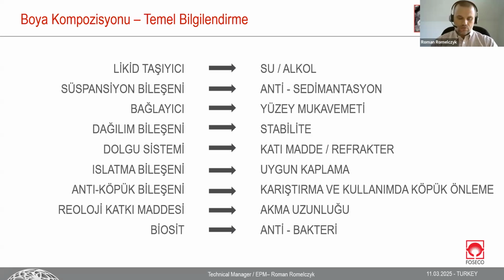Wetting agent, also a very important point. A wetting agent is nothing more than chemicals or materials which take care of the wetting angle. We can imagine we have PUCB cores, furan, alkaline phenolic, or others, for which release agents are also used, which are fatty. It means it's not always easy to cover them, especially with water-based coating. This is why the wetting agent is there, so the wetting angle is enough to cover the surface everywhere in the same way and build the same layer thickness everywhere.